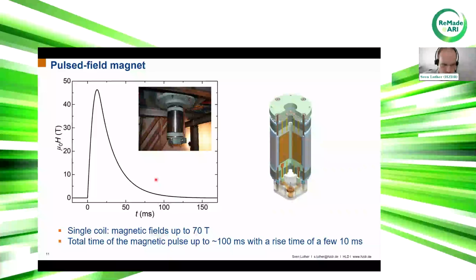So in our labs, we are running different pulse field magnets. The main magnets are these single coils, which can create magnetic fields up to 70 Tesla. So this is how the magnet would look like inside our lab. And then we have our typical pulse field shape. So this is the magnetic field depending on the time. You can see the total pulse is done within just 100 milliseconds, which has a rise time of a few 10 milliseconds, and then we reach the maximum field here.